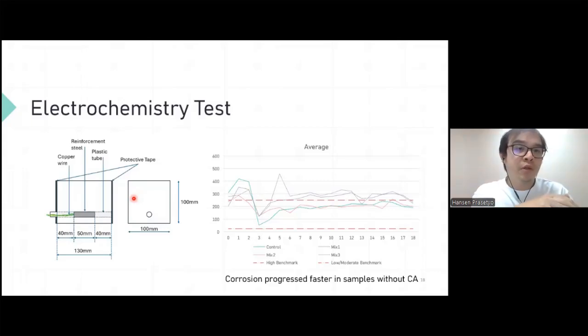But ultimately we want to measure corrosion in the steel bar. So we did an electrochemistry test. I made this sample. I just cast a steel bar, a reinforcement steel, inside concrete, and connected this reinforcement with wires, so we can measure the electrochemistry aspects of it. We put the samples in the sodium chloride solution. We did a 3-week cycle: 2 weeks in dry condition and 1 week in wet condition.